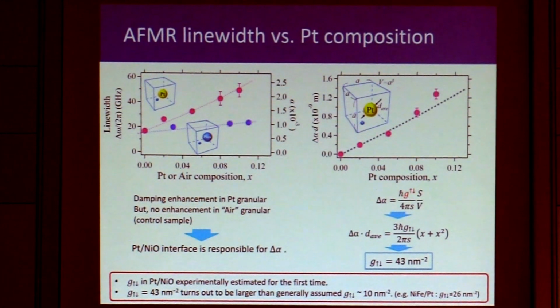So if you take a sample and you mix it with platinum, right? You will generate different kinds of disorder that will lead you to different inhomogeneous damping. Yeah, but I think this is the best we can do. Of course, we cannot really apply a field. I mean, we cannot do a similar analysis to the ferromagnetic case, because even if we apply the magnetic field, there is not much change in the damping and also the resonance frequency.